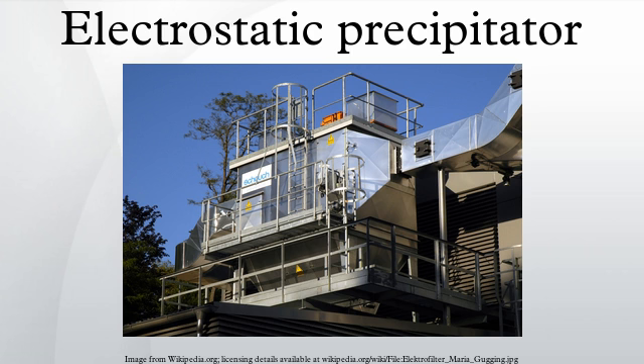High resistivity. If the voltage drop across the dust layer becomes too high, several adverse effects can occur. First, the high voltage drop reduces the voltage difference between the discharge electrode and collection electrode, and thereby reduces the electrostatic field strength used to drive the gas ion-charged particles over to the collected dust layer. As the dust layer builds up, and the electrical charges accumulate on the surface of the dust layer, the voltage difference between the discharge and collection electrodes decreases. The migration velocities of small particles are especially affected by the reduced electric field strength.